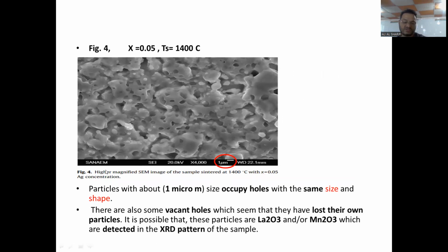Higher magnified scanning electron microscopic image of the sample sintered at 1,400 °C for this doping ratio. Particles with about 1 micro, well, it's bigger than nano because here it's equal to 10 to the power of minus 6, not minus 9, occupy holes. These particles occupy the holes with the same size, about 1 micrometer, and shape.